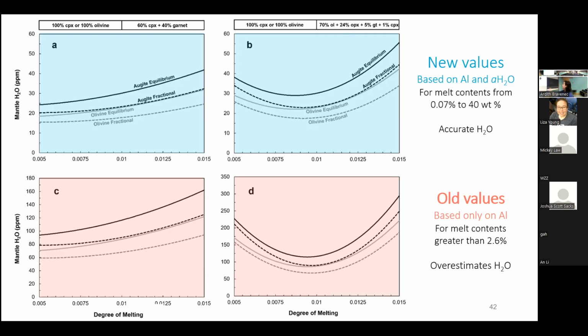And as you can see here, using my new model, we obtain much lower interior water contents than the old parameterization just on aluminum, which systematically yielded much greater values. And that makes sense because that old model was only calibrated on samples that initially contained about 2.5 or more weight% water content from the start. So they were very hydrous. And if you run a model that's only been calibrated on higher values, it's probably going to return higher values. But we don't necessarily know that the Martian mantle is very hydrated. So that's not an assumption we can make.